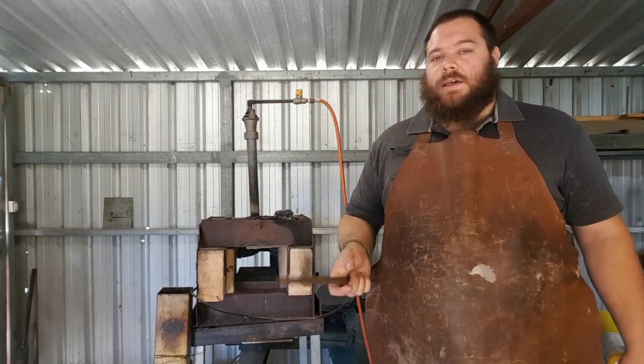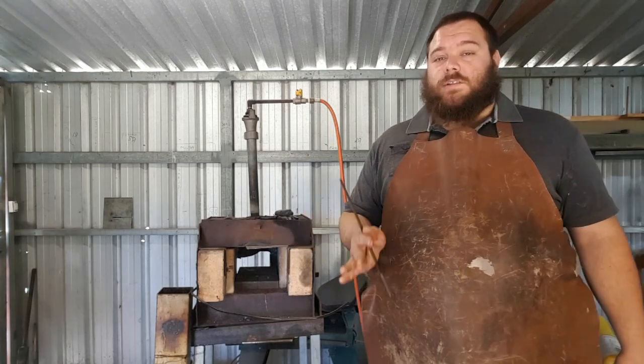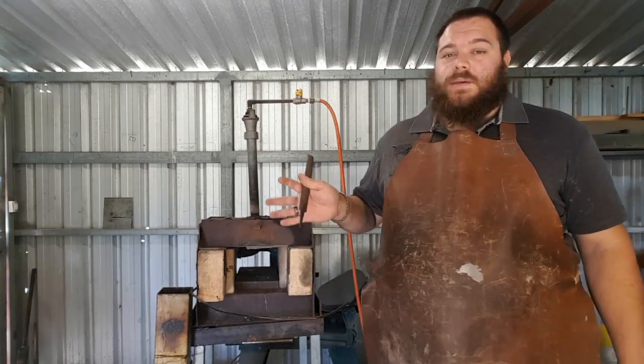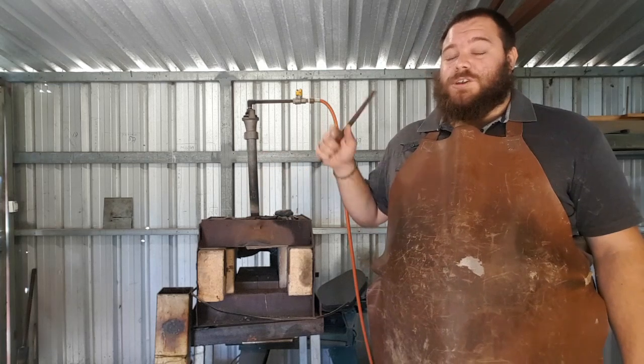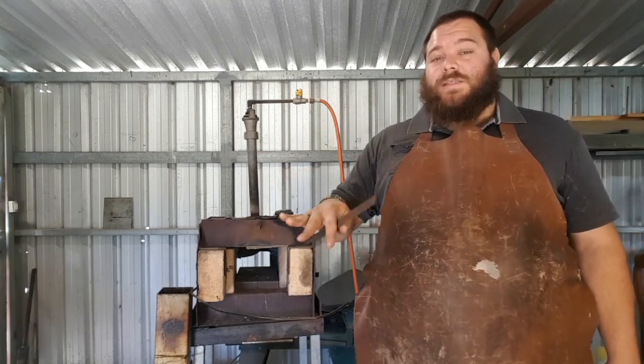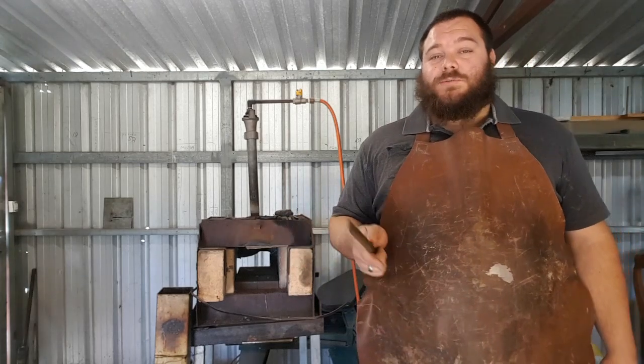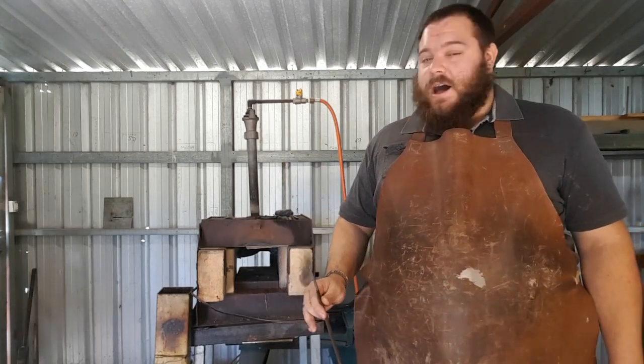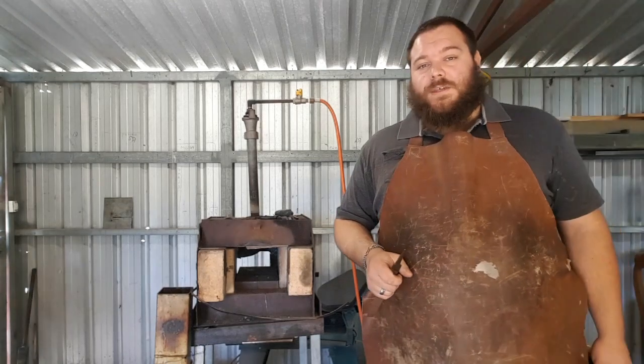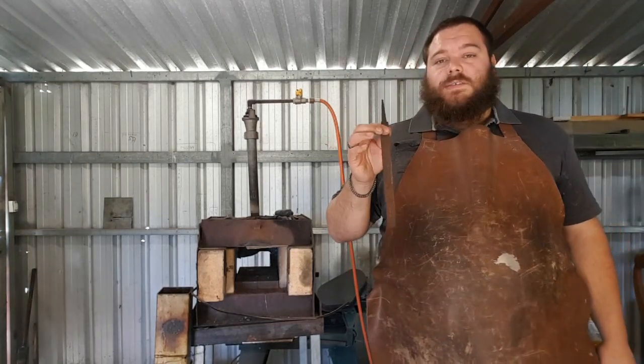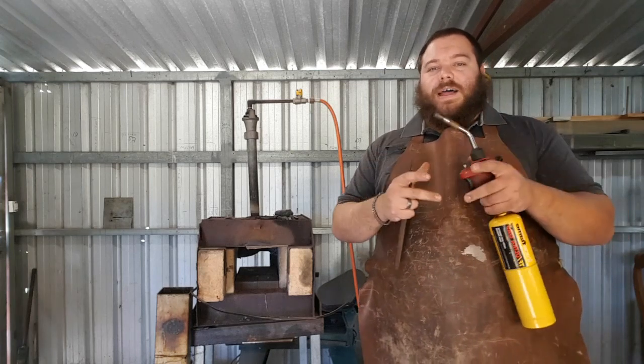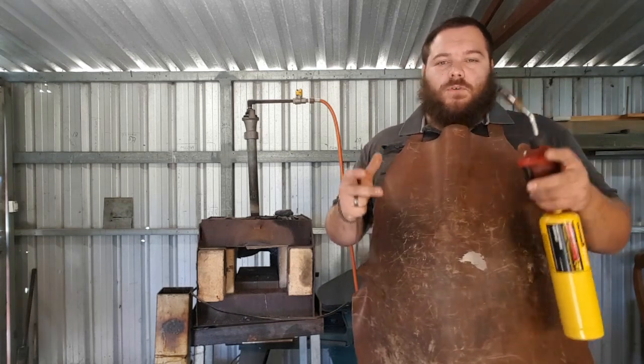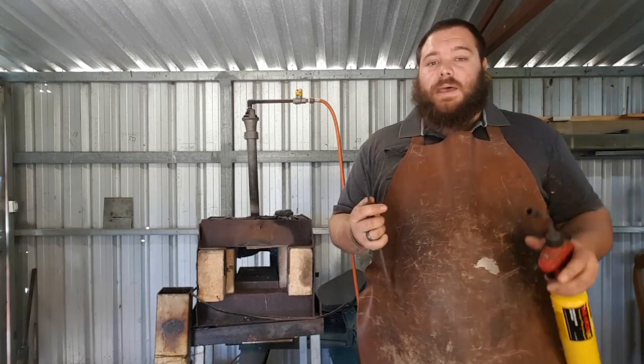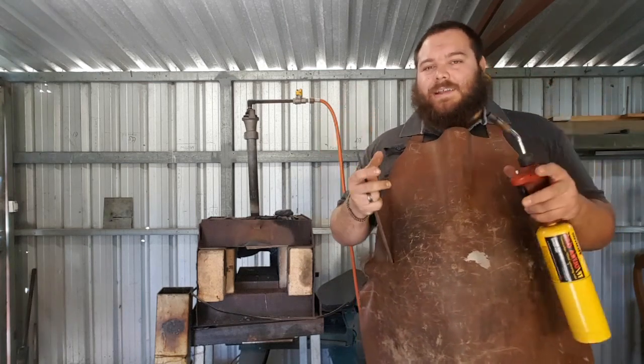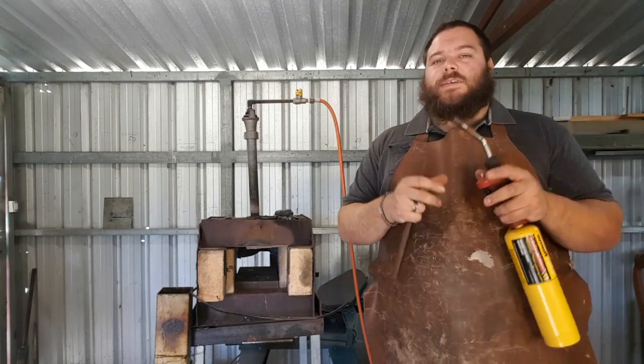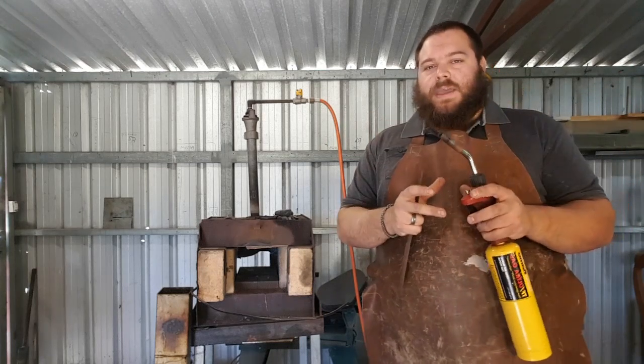It is not annealing. Annealing is heating to critical temperature and letting it cool very slowly. And that you can do with the gas forge very easily by just letting it heat up to critical temperature in the gas forge and then shutting the gas forge off and letting the forge cool down with the material in it. Or you can heat it up to critical temperature and stick it in vermiculite or perlite. I don't do that myself because I just tend to do the forge method. But normalization simply relaxes the grain structure. All of that stress you've put into it through the forging steps or through the manipulation steps, or if it's an unknown steel, relax that grain structure, shrink those grains, and make it a much finer piece of steel.